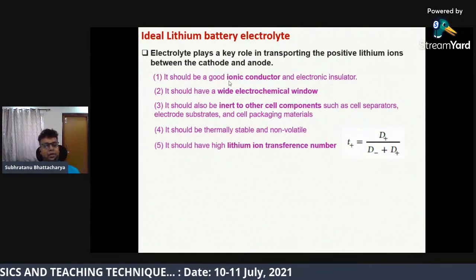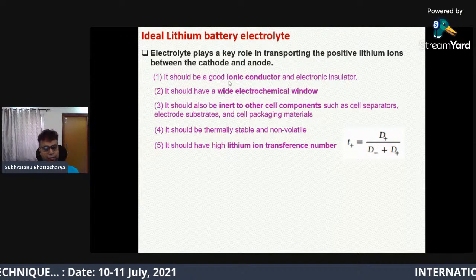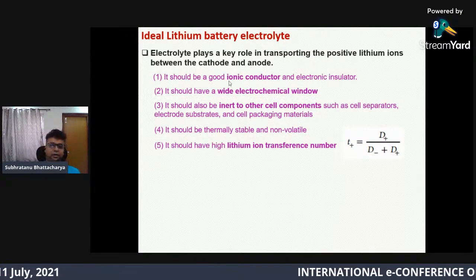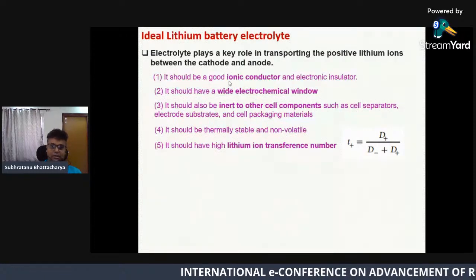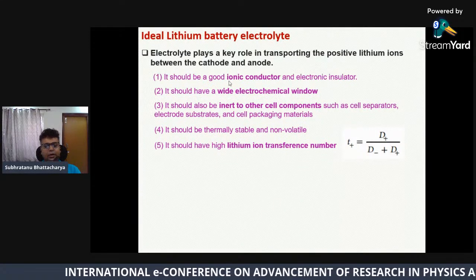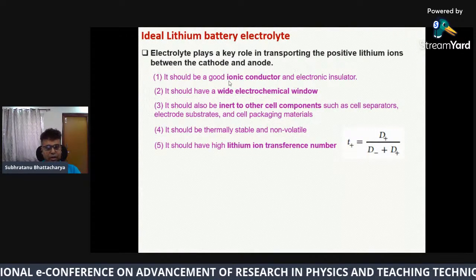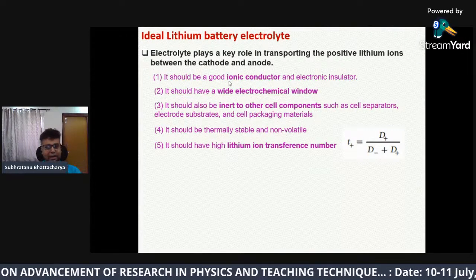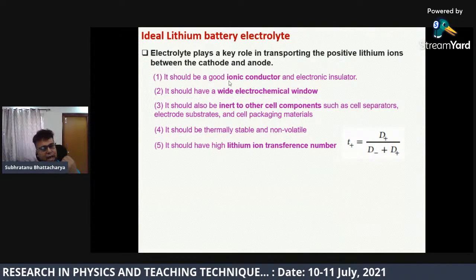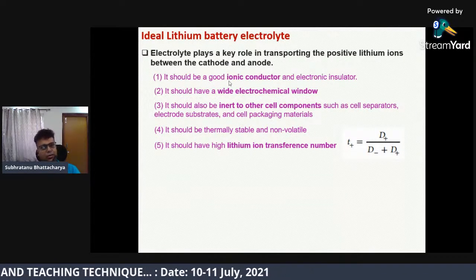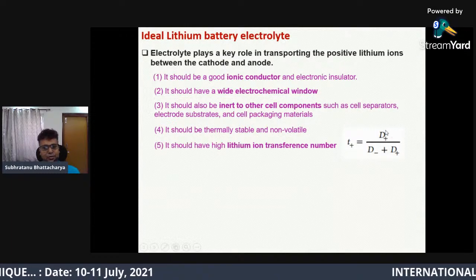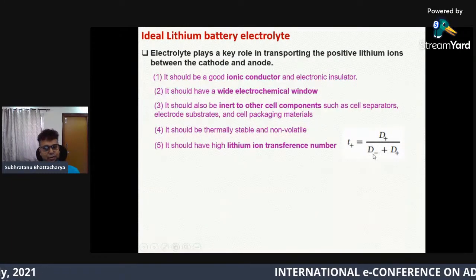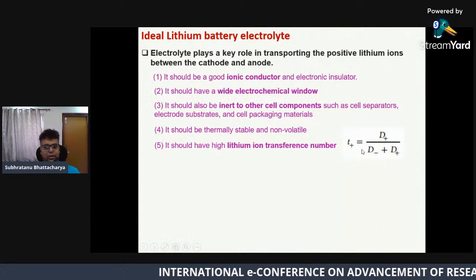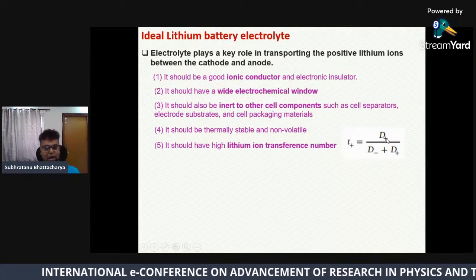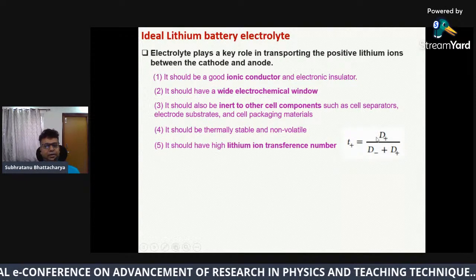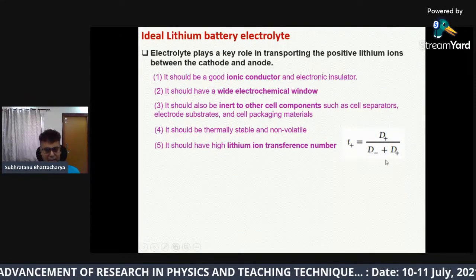But if you consider that the electrolyte is actually nothing but a solution of a salt, that is a lithium salt, in a solvent. A lithium salt has both anion and cation, so you can get anionic conductivity as well as cationic conductivity. This is the diffusivity of the anion, and this is the diffusivity of the cation. The transference number of the cation is the ratio between the diffusivity of the cation and the sum of the diffusivities.